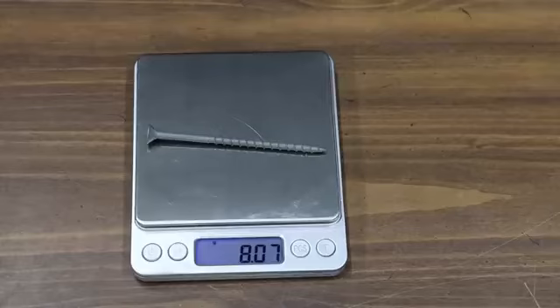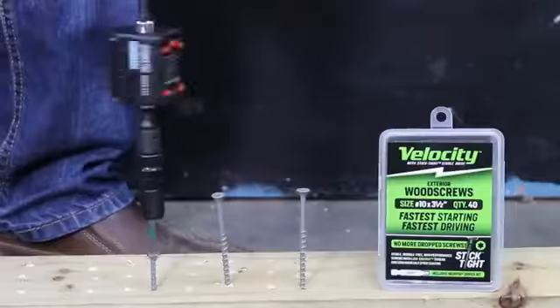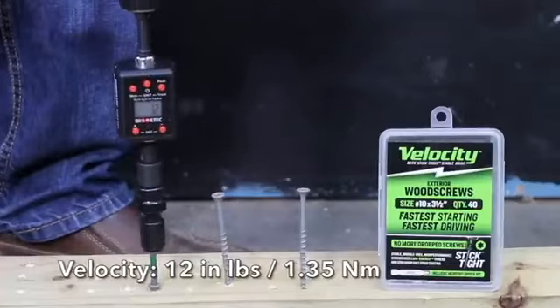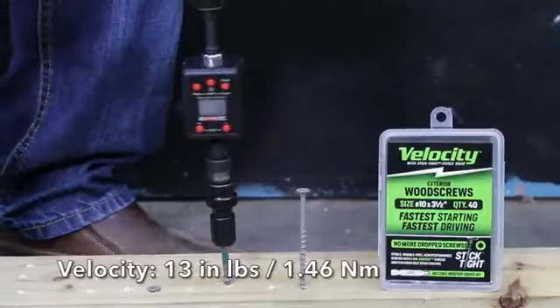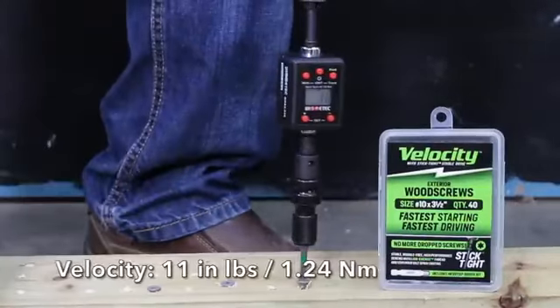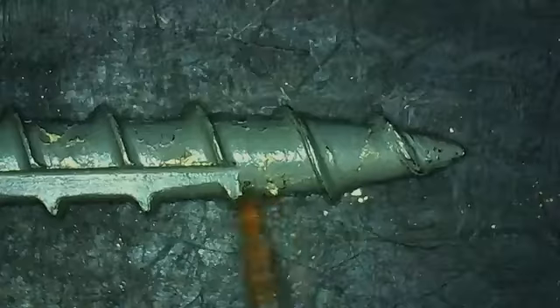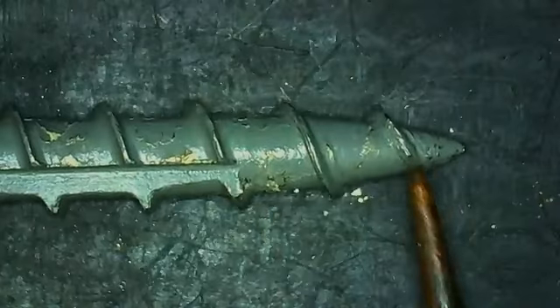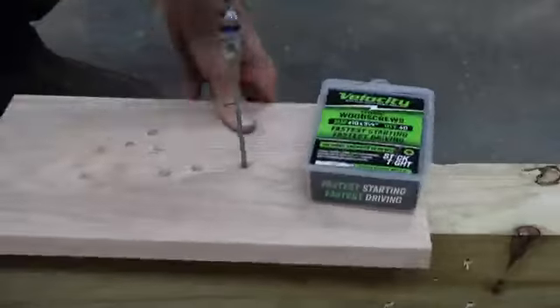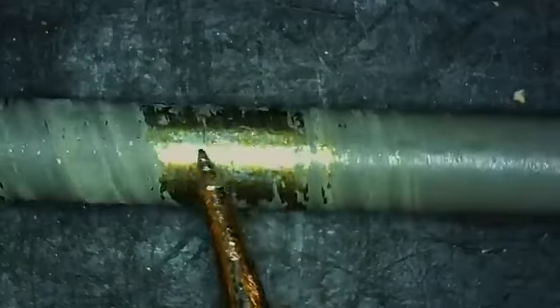The Velocity weighs 8.07 grams. Only 12 inch-pounds to drive the first screw, the least amount of torque yet. 13 inch-pounds on the second screw. 11 inch-pounds on the third screw for an average of 12 inch-pounds. And the Velocity's coating didn't hold up quite as well as some of the other brands. And the oak caused a lot of damage to the coating on the Velocity with lots of metal exposure.